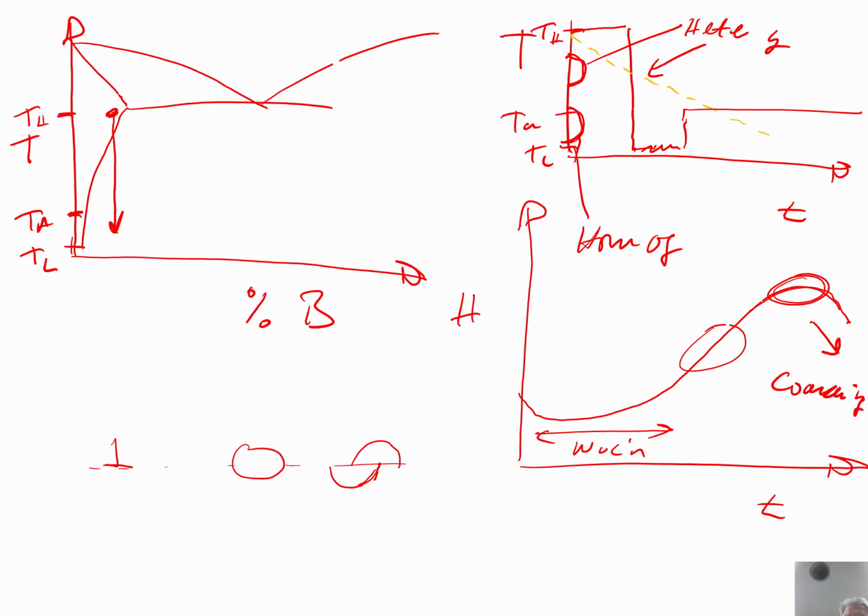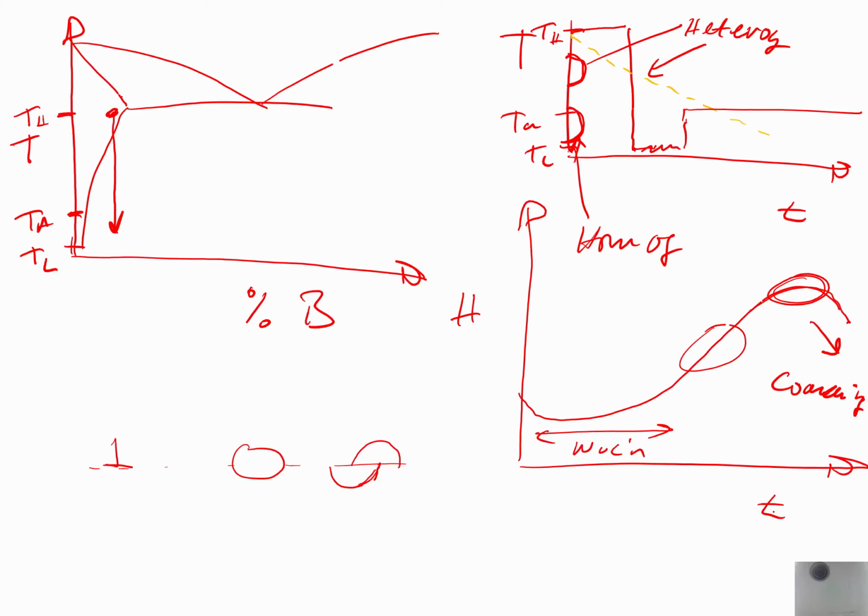There's homogeneous nucleation down here. What does heterogeneous nucleation mean in this context? Well, in that context, heterogeneous nucleation would mean basically precipitating out the beta phase on grain boundaries. Is that a good thing? No, for two reasons. Number one, you waste your alloying elements putting them on the grain boundaries. Secondly, you may end up embrittling your material by forming large intermetallics along the grain boundaries, giving yourselves a brittle path.